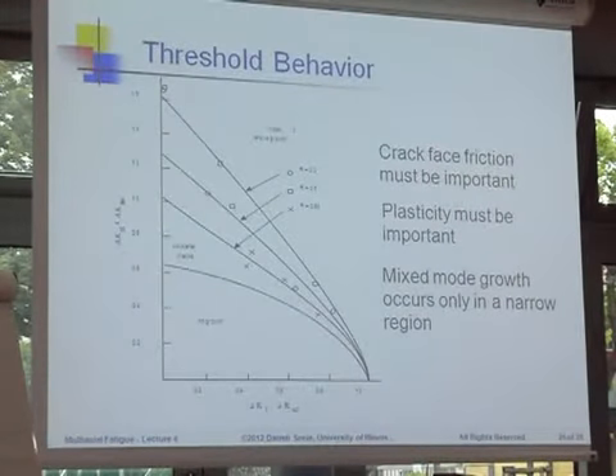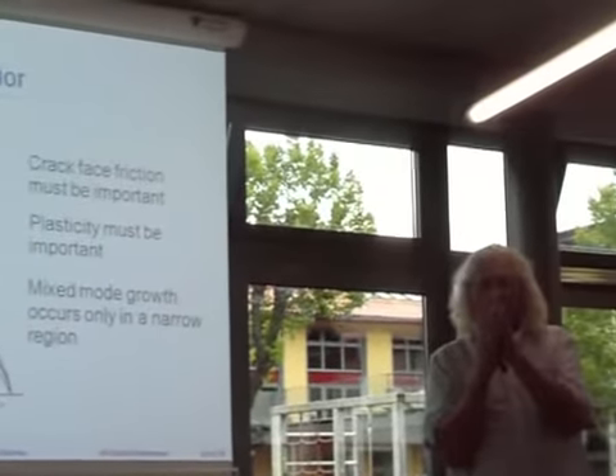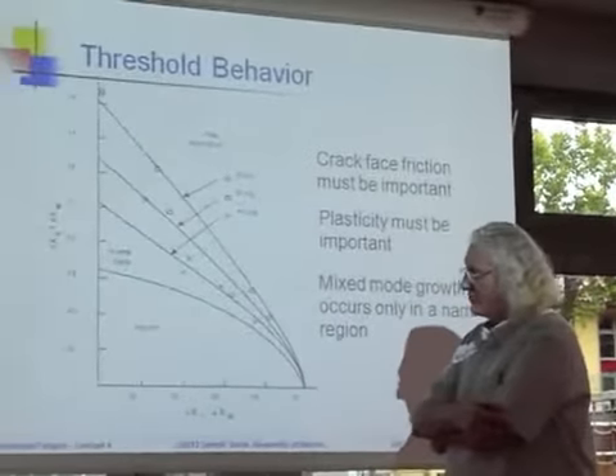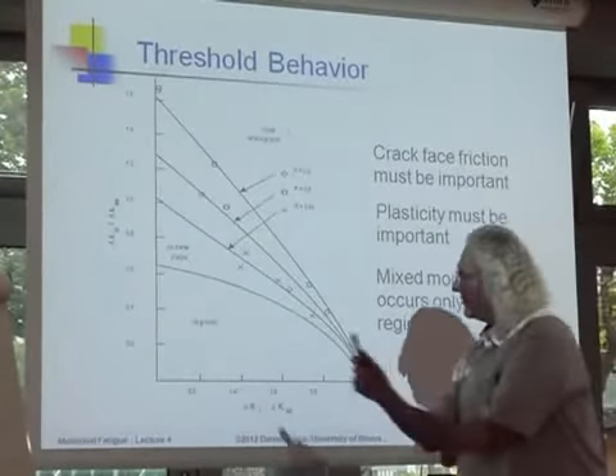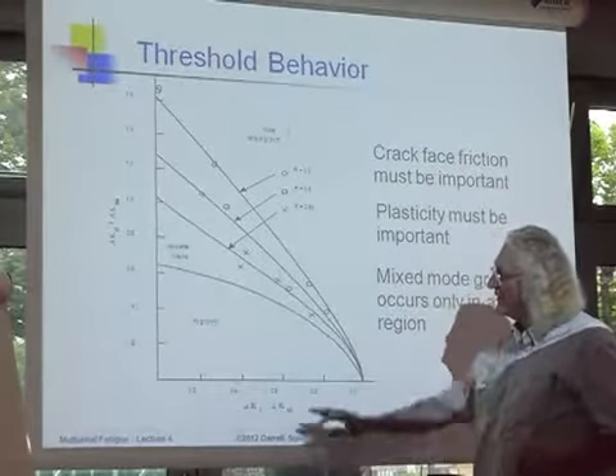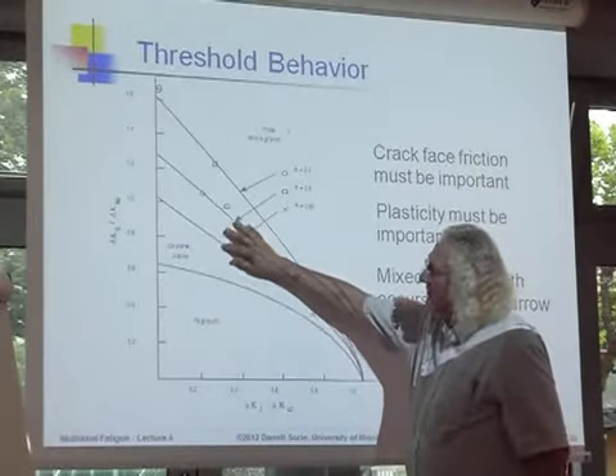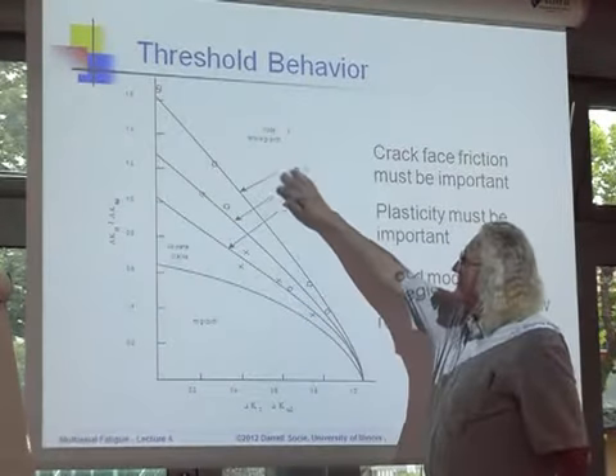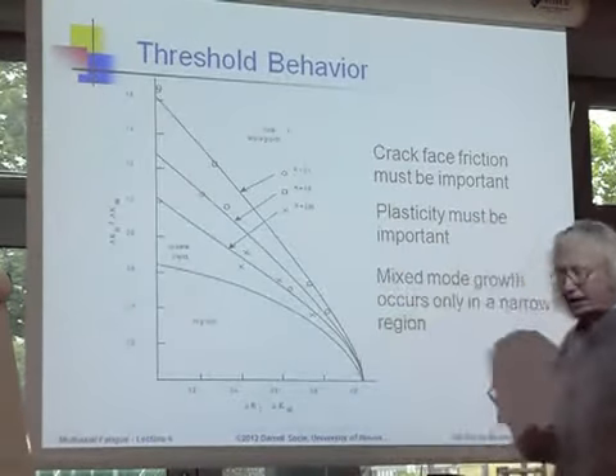There's also a lot of people who worry about mode 2 and mode 1 thresholds. They suffer from the same problem of this shear closure force. If you want to know the threshold in mode 2 of a standard test specimen, it's easy. But transferring that to any other situation is not so easy because of the changes in crack-face friction. And again, you see the same kinds of ideas for threshold stress intensity as you do for long crack growth. Plot K2 here and K1 here: a region where nothing happens, a region where you get shear cracks, and a region where you get tension cracks.